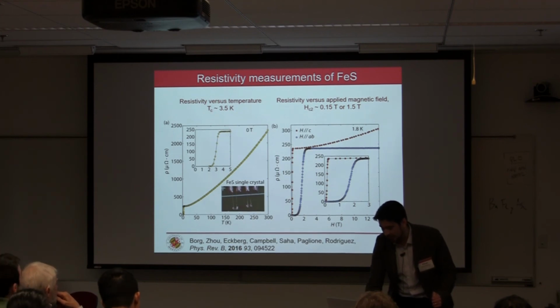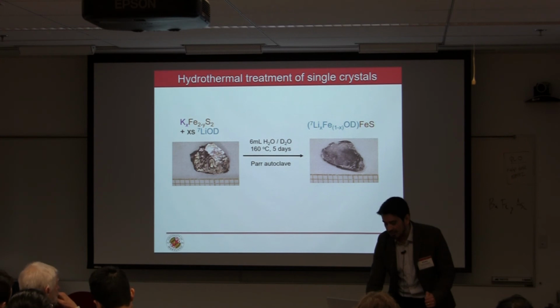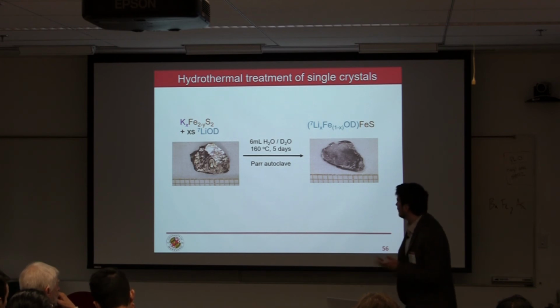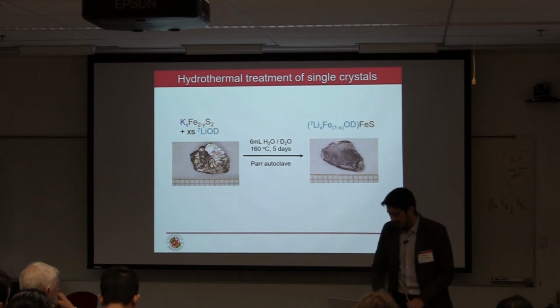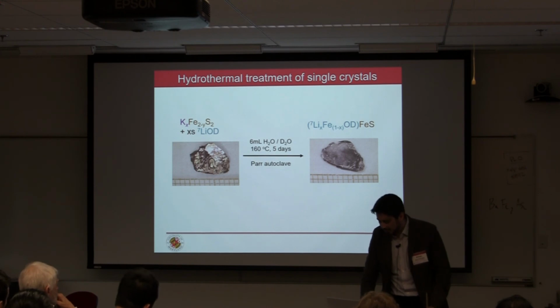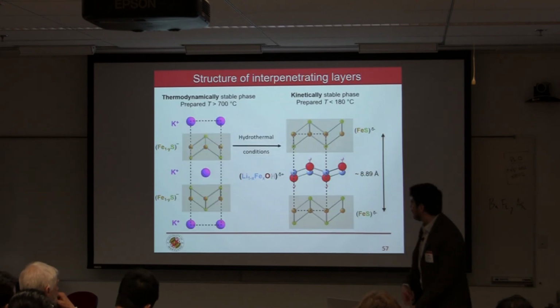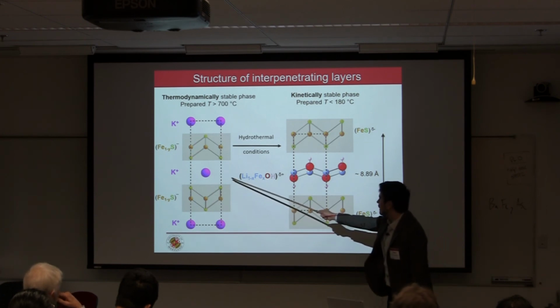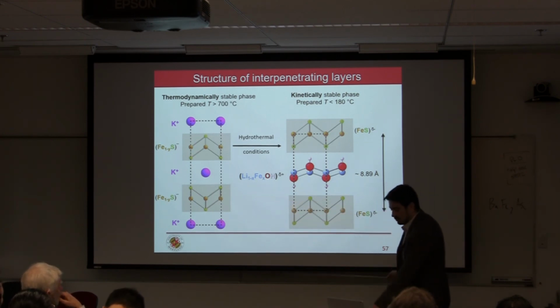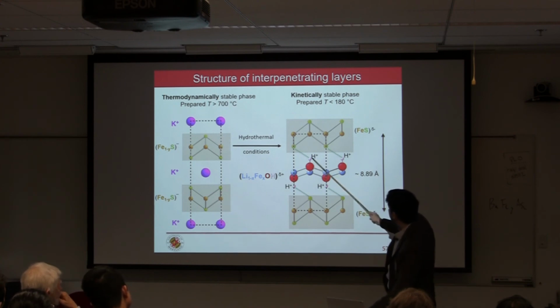It tends to be lower than the selenide, about 3.5 Kelvin. It looks to be a somewhat different superconductor than the iron selenide. What you'll see in the lab tomorrow is that you convert it from the potassium iron sulfide, a gold-like mass in its reflectivity, over to something that looks like a dull gray one when you do hydrothermal. And this is just what's happening crystal structure-wise. You're taking out potassium under hydrothermal conditions, and you're stabilizing it, we think, through hydrogen bonding of the lithium hydroxide to the iron sulfide layer itself.